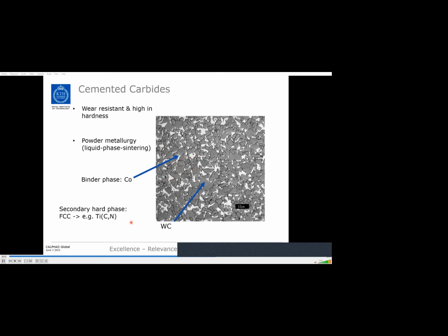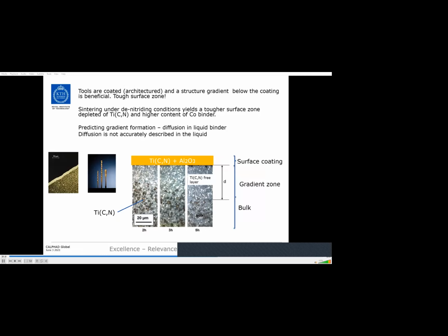And then usually there are also secondary hard phases with FCC structure of various cubic carbides or carbonitrides. So those tools are, for various reasons, made with a structure gradient. After having this structure gradient, they are coated, and that gives you a rather tough material, well, at least a tough surface zone. And it turns out that if you do the sintering under denitriding conditions, you get a tougher surface where there are no cubic carbides and there is a higher content of the cobalt binder phase.